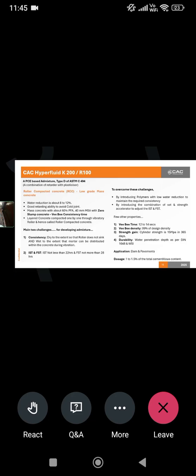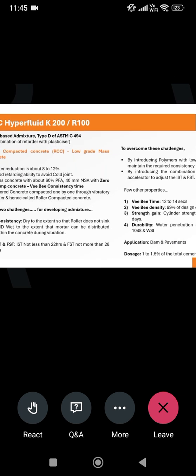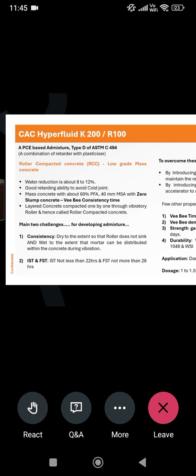Mass concrete, and you know that water reduction is 8 to 12%. Good retarding ability to avoid cold joints because the admixture is retarding type. You can see that it is a type D of ASTM C494, and mass concrete with about 60% PFA, 40 MSA with zero slump concrete.